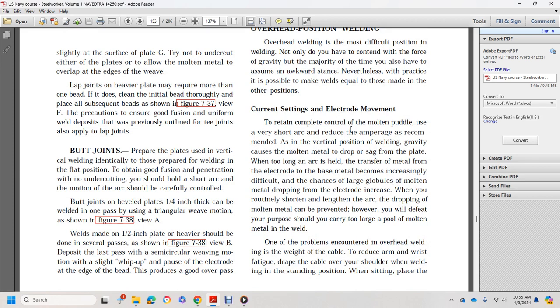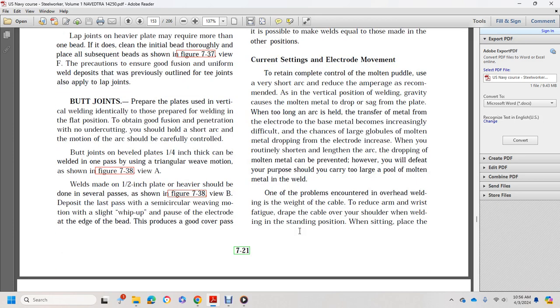As in the vertical position of welding, gravity causes the molten metal to drop or sag from the plate. When too long an arc is held, the transfer of the metal from the electrode to the base metal becomes increasingly difficult. The chance of large globs of molten metal dropping from the electrode increases. When you routinely shorten or lengthen the arc, the dropping of the molten metal can be prevented. However, you defeat your purpose if you carry too large a molten pool of metal in the weld. One of the problems encountered in overhead welding use the weight of the cable to reduce arm and wrist fatigue.